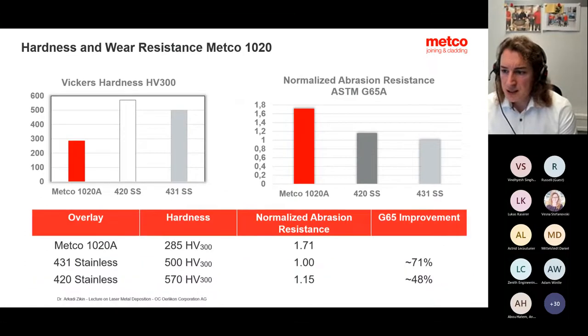Also, our testing results indicate, if we do a direct comparison of those materials in terms of hardness, 1020, for example, really drops the hardness values compared to, as I mentioned before, 400 series steels. But even in a simple ASTM G65, you get an extremely increased wear protection compared to both of those alloys.